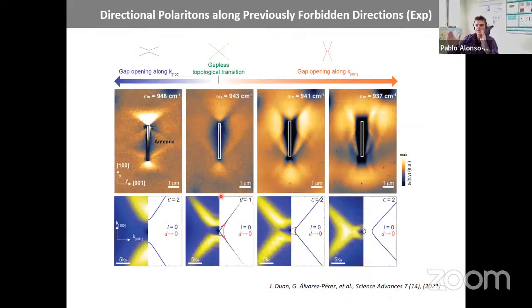Interestingly, we tracked the transition between the propagation along the 1, 0, 0 direction that is indicated here to the propagation along the 0, 0, 1 direction. And we saw these striking near-field images where we have these cones. And when we did the theoretical analysis, we saw the L equal to 0 mode was the one transiting from the 1, 0, 0 direction to the 0, 0, 1 direction. It is closing to the center. It closes here, and then it opens again, but it opens rotated. So you can see here that it's rotated to this side, and here it was like this. So it goes from one side, it closes at 0, and then it opens in the other direction, 90 degrees. And this is what is called an optical topological transition, because the topology of this open curve is different from this one that is crossing at one point.